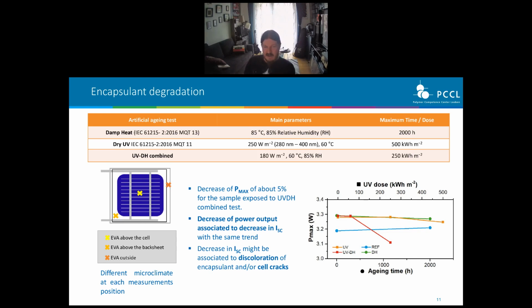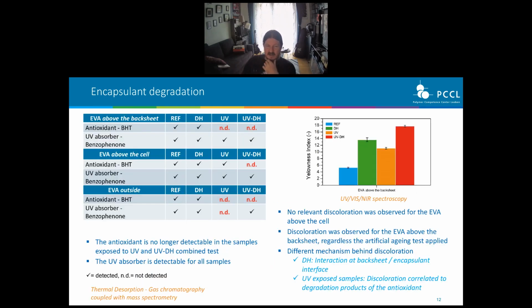What we found is that after the UV damp heat test, this module lost about 5% of its initial power. After the damp heat test, we didn't observe any power loss, and a slight power loss was observed just after the UV test. What we especially saw decrease was the short circuit current, which is usually associated with discoloration or cell cracks. So we took a closer look and did an additive analysis.